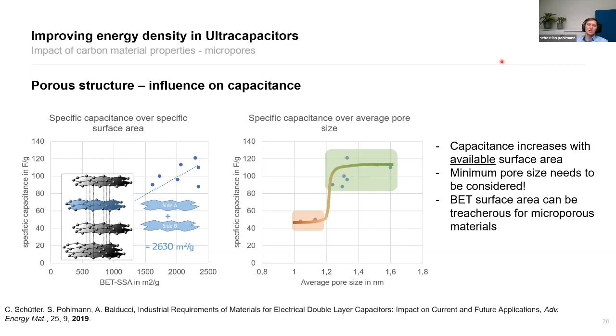If you have a carbon material, then the maximum surface area that you can get is that of flat graphene, and that is 2,630 square meters per gram. If you get a higher value, it is because the BET surface area is very treacherous when you go into microporous materials. The BET calculation does not really treat the micropores well, especially if you have very small pore sizes, around 1 nanometer, higher and lower. There are a lot of effects. I trust you to read up on this topic if you are interested, because that is another 10 talks on its own where you can talk about BET surface area.